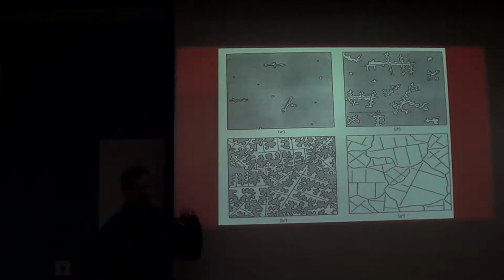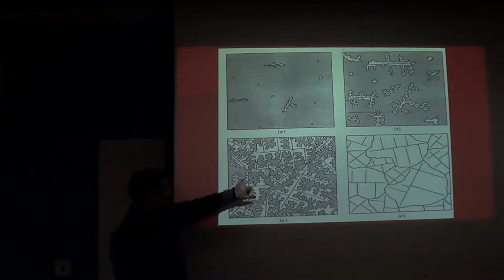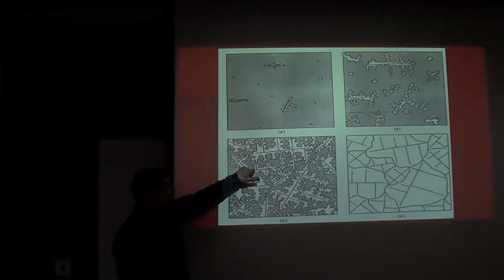So I showed earlier the segregation that we can measure throughout the cross-section of the ingot. We call that macro segregation. But if we had the right analytical tools, we could actually see that there's slight differences in composition between these dendrites and this remaining liquid as well.